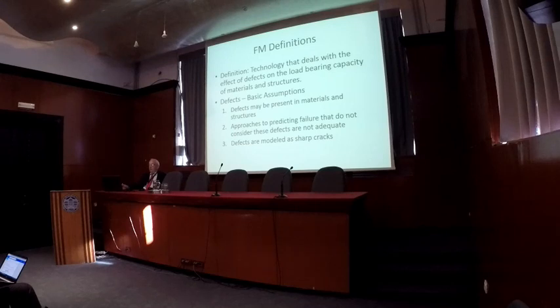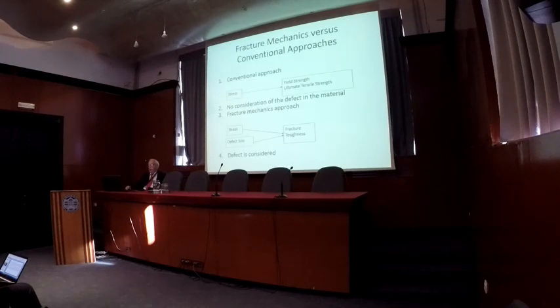Here's a definition, and this is sort of my own definition, but I heard people like George Irwin use this: fracture mechanics is a technology that deals with effect of defects on load bearing capacity of materials and structures. The basic assumption in fracture mechanics is that your material or your structure may have a defect, and if it doesn't have a defect, the defect may become present during the service time. So defects are modeled as sharp cracks. That's part of the basic assumption of the fracture mechanics approach, that there could be a sharp crack in the structure.